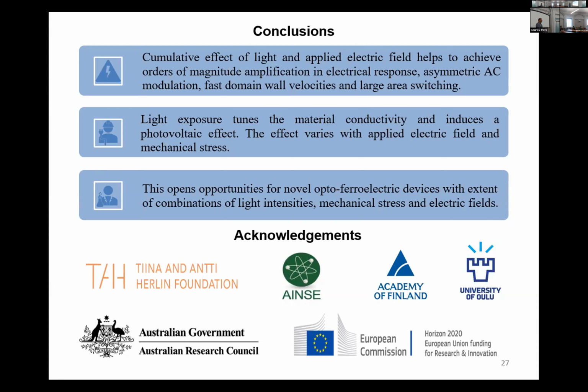Also, you showed that you can mechanically tune the samples. So, did you apply mechanical stress using the AFM tip? Yes. So what I'm doing is when we make contact with the tip, we can decide the set point where we can increase the stress from the AFM tip. And the same tip scans over the area. But with this kind of measurement, one needs to be very careful that the tip is not wearing out, because if the tip is very sharp, say for example in the first measurement the diameter is 30 nanometers, but after a few scans, it becomes 60 nanometers.